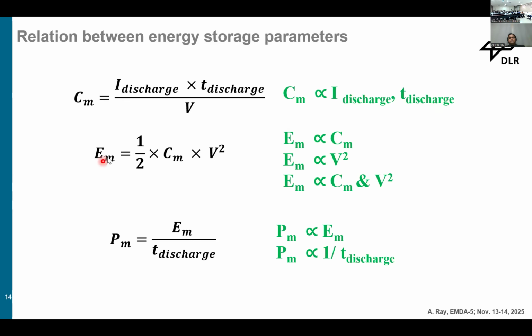And the most important thing is the energy density. There are two ways you can increase the energy. One way is to increase the capacitance of the material, or another way is to increase the voltage of the device. The voltage mainly depends on the electrolyte that you are using. Energy density is proportional to the square of the voltage. So sometimes people are most interested in using different types of high voltage electrolytes to improve the energy density, and also the power density.